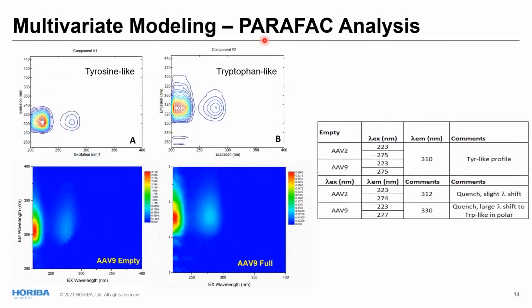So again, we head into multivariate analysis because we'd really like to understand the mechanism of what we're seeing, what's causing these shifts. You can see shifts in protein signatures that might be caused by, for instance, the hydrophobic or hydrophilic environment, or in this case, what we found with a PARAFAC analysis, which is kind of an extended multivariate PCA analysis. So a fairly simple to understand analysis.